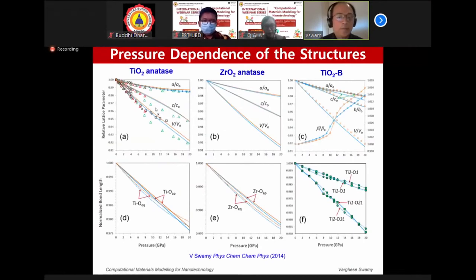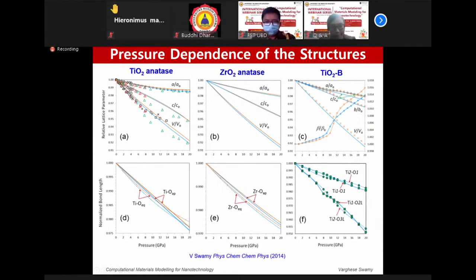Now, if you compute the pressure dependence of the structure of these metastable phases, you can more or less reproduce the lattice hardening in the case of anatase. You can see that the structure evolves and then flattens, it becomes harder to compress along the A axis, while along the B axis, along the C axis, it is evolving normally and becomes easier to compress with pressure. If you look at the zirconium equivalent, you don't see a similar case. You see a smooth evolution of the lattice parameters with pressure.